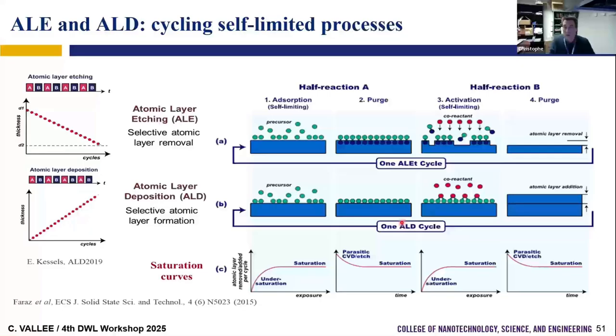So this is what we develop for atomic layer etching, with the same design as atomic layer deposition, in that we have two steps of reaction. So we pulse the gas, and during the first gas precursor, we use it to modify the chemistry at the surface of the substrate. And thanks to the modification of the chemistry, we use a second pulsing to have energetic ions, and we do a sort of selective etching. We only remove the layer that has been chemically modified, and we don't remove the layer below. So we only remove, for example, one monolayer. If every time we modify one monolayer, at the end of the process, we only remove one monolayer, and then we repeat as many times as we need, depending on how many monolayers we want to remove.